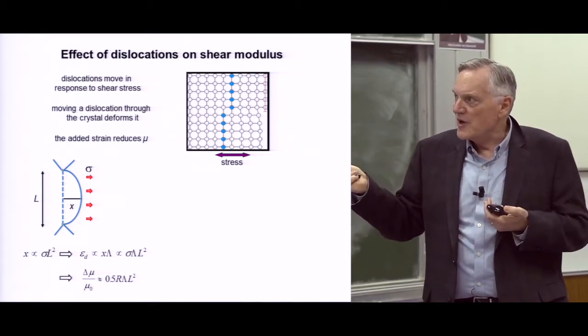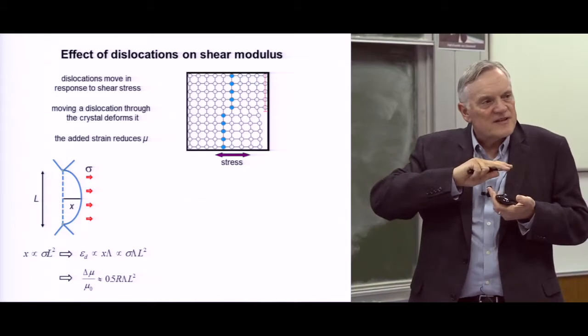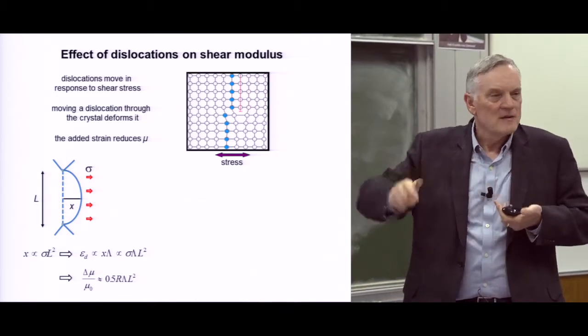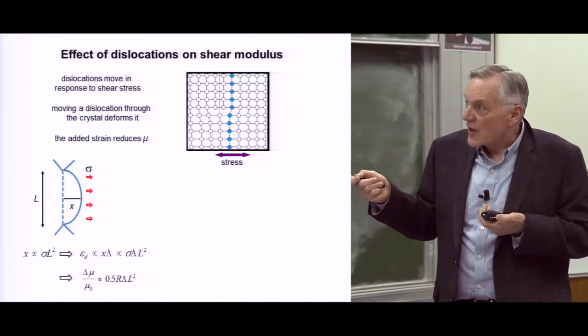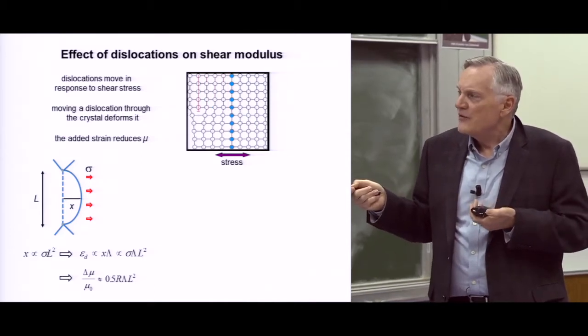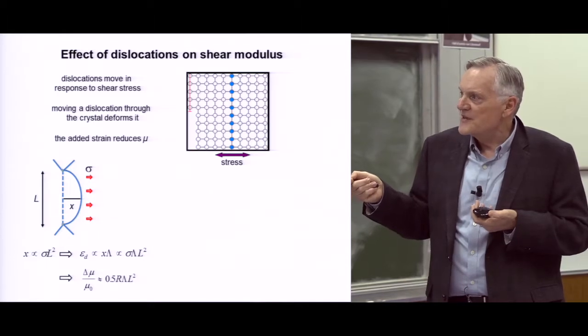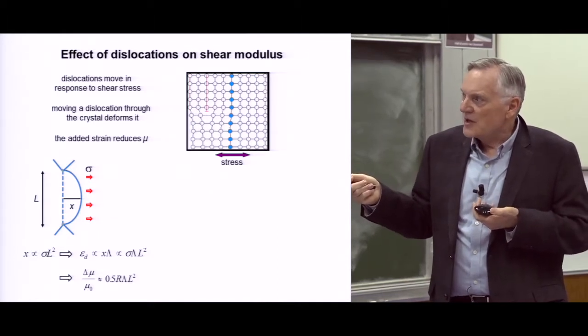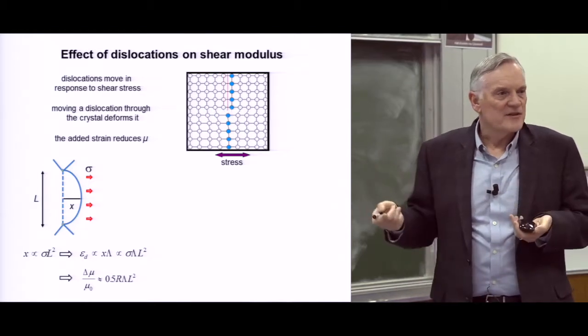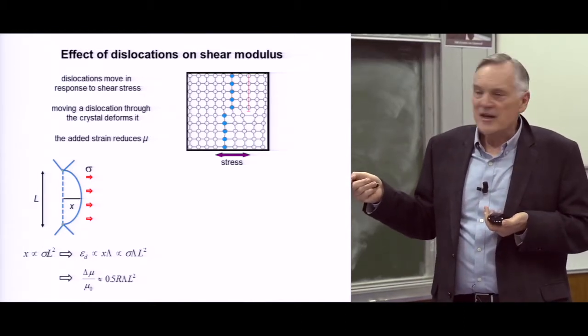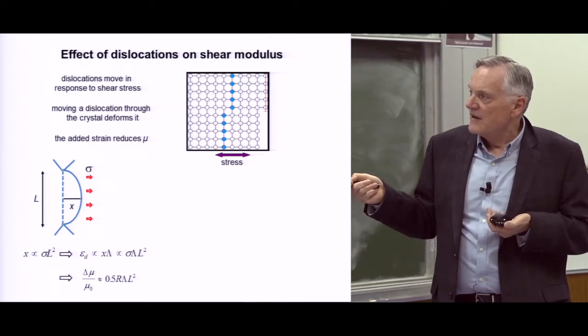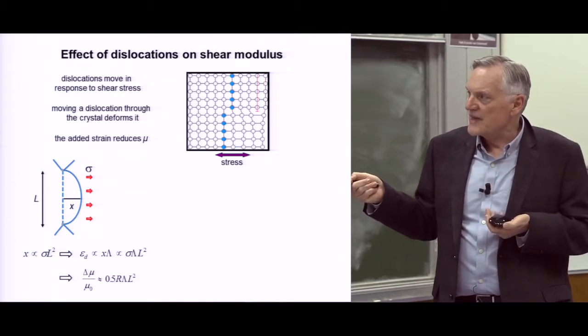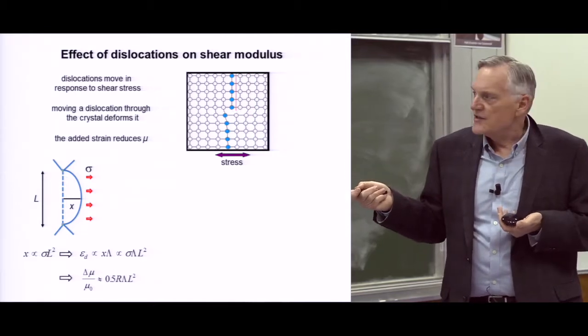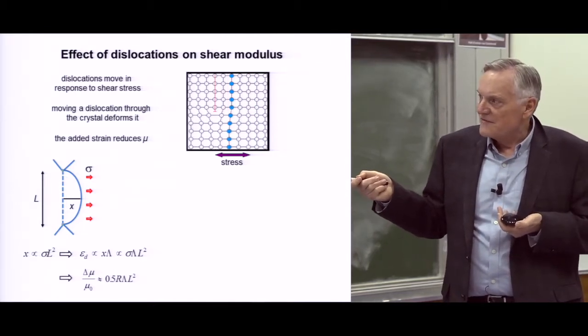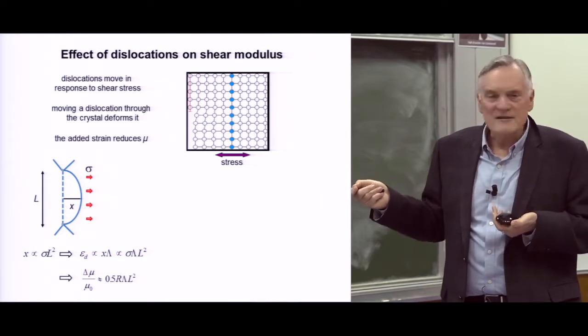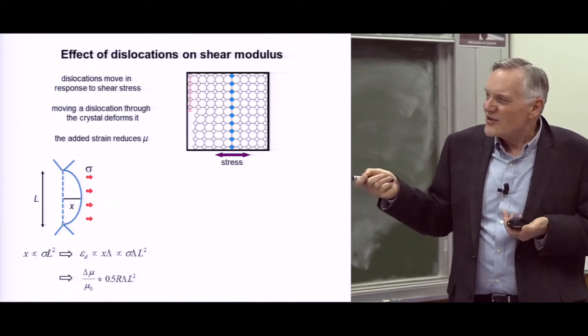So the area swept out here, this area in here, that's the part of the crystal that's slipped by one atomic space. And that area is proportional to the square of the length and proportional to the stress. So if you multiply how far out it moves on the average and multiply that by lambda, which is the total length of dislocations in the crystal, the density, that gives you how much strain you've got. It's proportional to the density of the number of dislocations per square centimeter times the average length of the dislocations. And so the shear modulus, if it slips by this much, the shear modulus is proportionally reduced. And it turns out that can be huge.